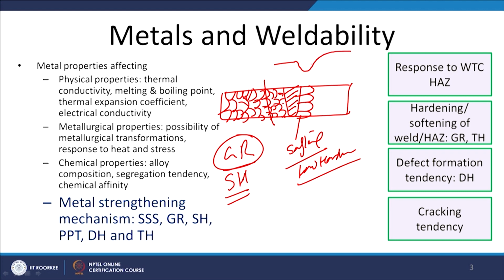So, the HAZ softening can be observed significantly in case of the grain refined metals subject to fusion welding, and a similar effect is also observed in case of the deformation based approach, where a lot of heat is generated. If the heat generated during the deformation based approach of the welding process is very limited, then in case of the grain refined materials, the heat affected zone properties will not be much affected.